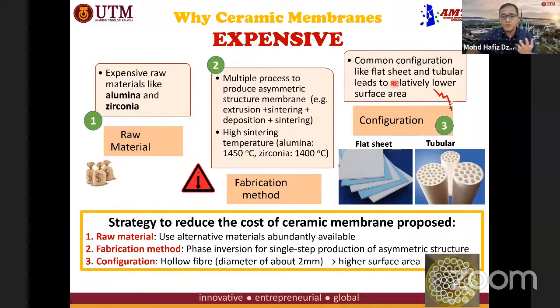So therefore, strategies to reduce the cost of the ceramic membrane have been proposed by many researchers. You can use alternative materials that are readily available at low cost to replace alumina and zirconia, or we can also use the phase inversion technique to produce an asymmetric structure in a single step. Okay, I will talk about it later. And by using this phase inversion, you can produce a structure that we call hollow fiber.